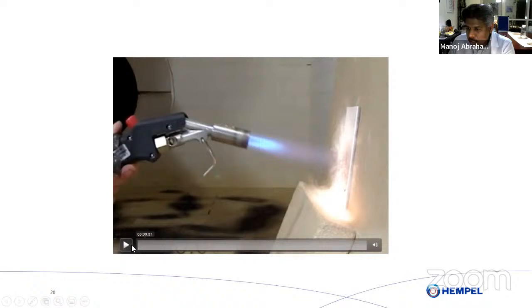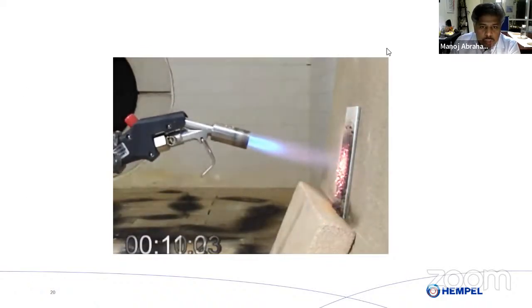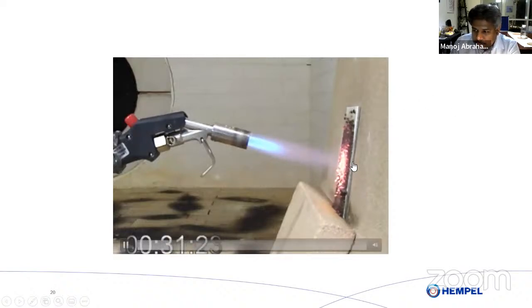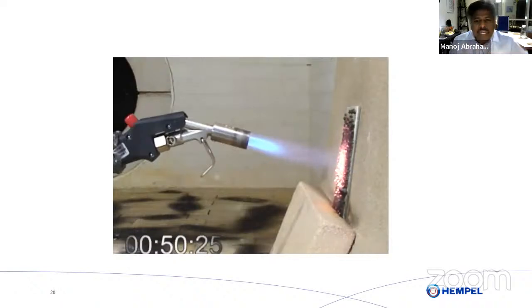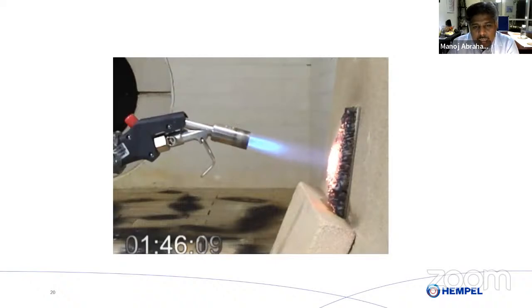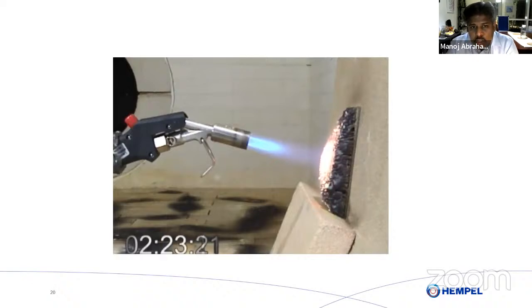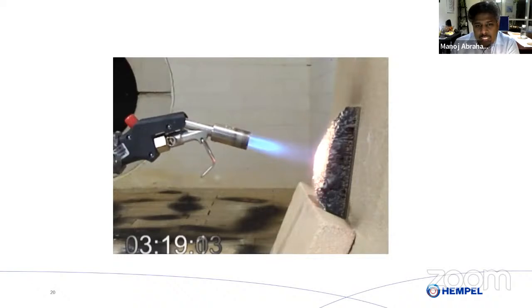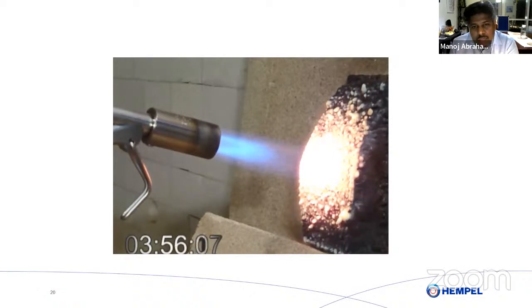Let me show you another short video. Just watch the intumescent coating applied here on the plate. This is what happens, right? You have heat coming in from the outside on the coating, and just see what happens to the coating. You can see that the coating slowly expands, and the expansion is usually 40 to 60 times its original thickness. If you have applied a 1 millimeter thick coating, it will expand to about 40 to 60 millimeters. It is red hot on the outside, but you can still see that the char is a stable char, and it prevents the heat from flowing inside.